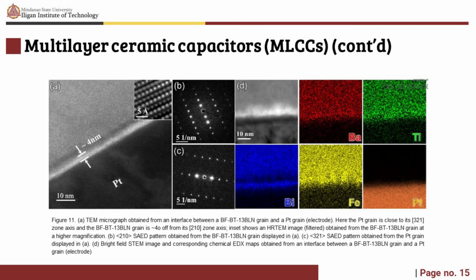Figure 11a shows a TEM image obtained from the interface between the BF-BT-13BLN ceramic and Pt, or platinum, electrode. According to the selected area electron diffraction, or SAED, patterns in Figure 11b and c, the ceramic grains are perovskite structured.